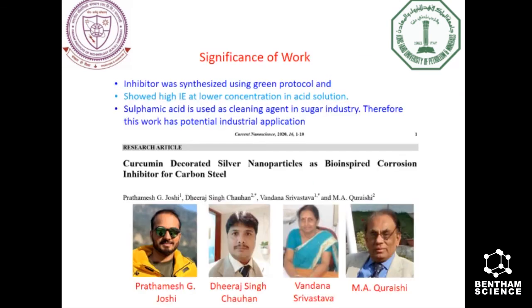The major significance of the present work was that the inhibitor was synthesized using a single-step green protocol and showed a high efficiency at low inhibitor concentration in the acid solution. And this work has a potential industrial application because sulfamic acid is used as a cleaning agent in sugar industry. The title of this work is Curcumin Decorated Silver Nanoparticles as Bio-Inspired Corrosion Inhibitors for Carbon Steel.